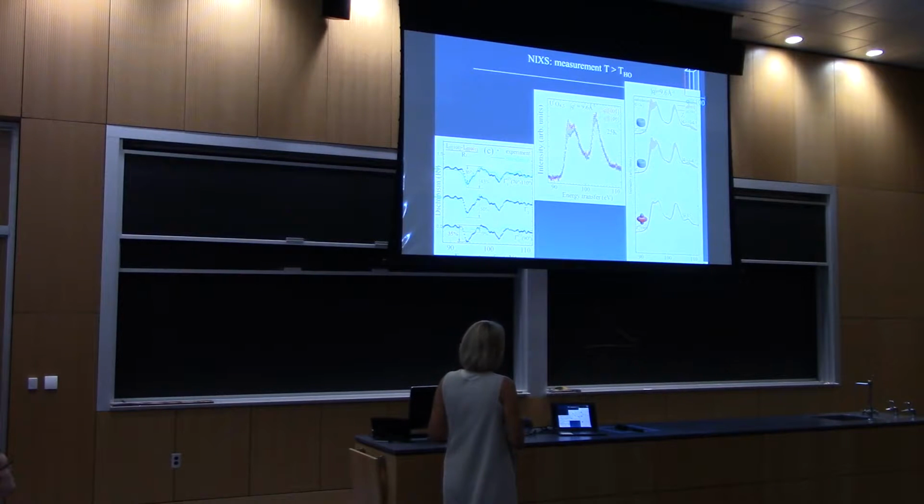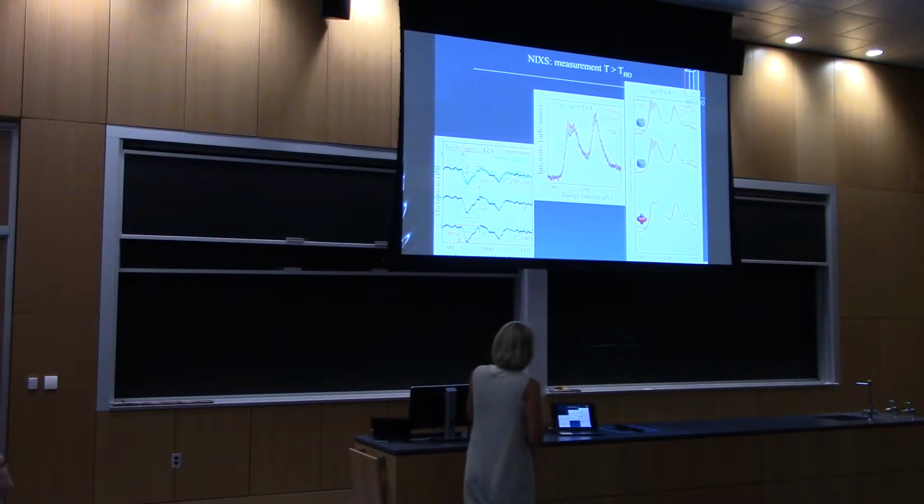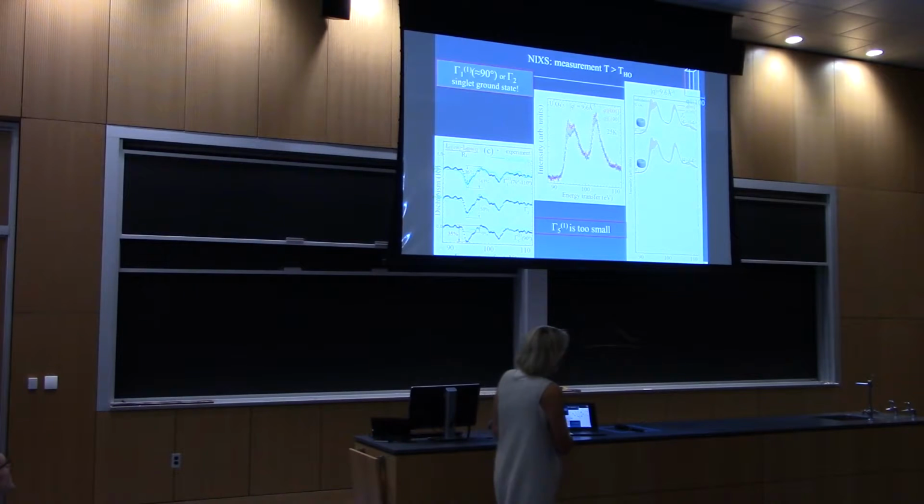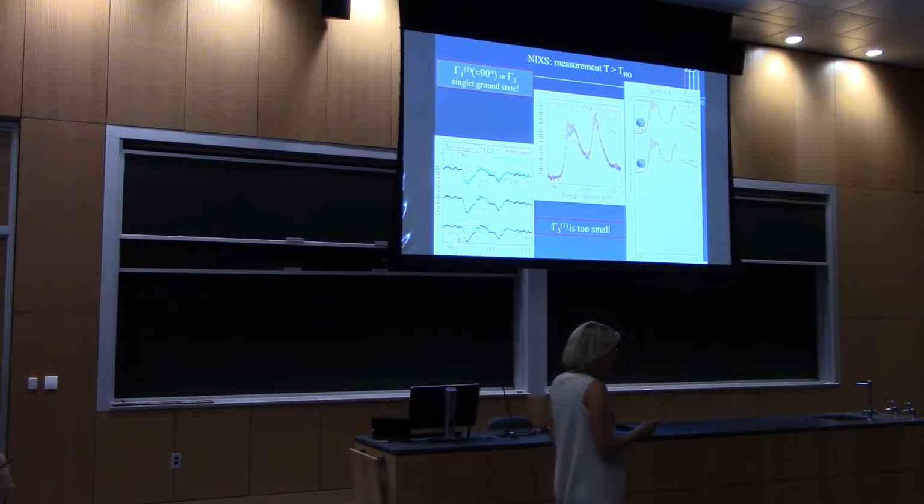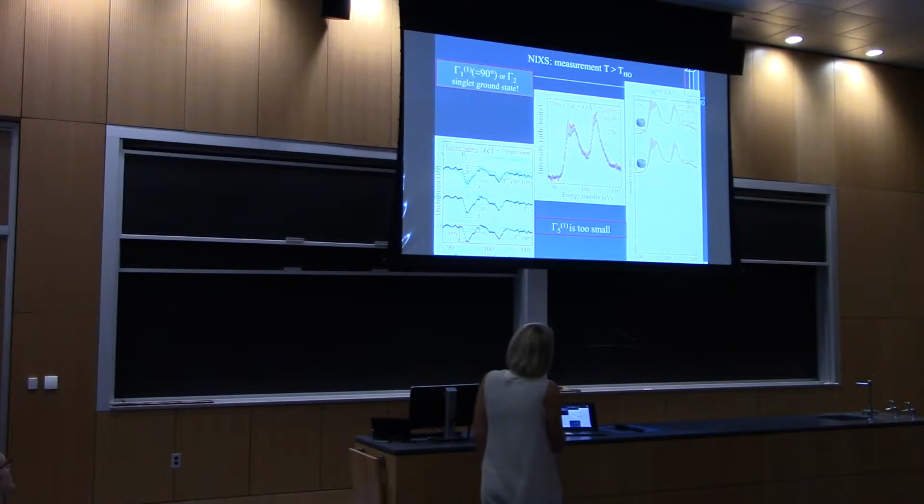The percentage we construct basically is from minimum to top to a certain peak ratio in the isotropic spectrum. That's why we give it in percent. So the measured one is 35%, and it is clear that the gamma 5, although this is the best case, gives a dichroism which is far too small. So then you also have to eliminate the gamma 5 as the ground state. And we're left with these 2 states.